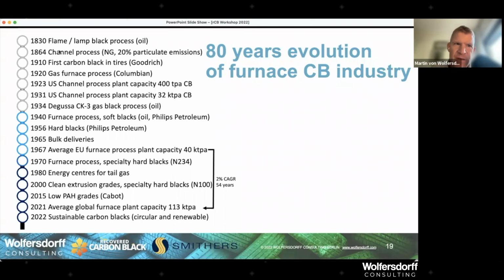But in 1830, we had the lamp black process with the feedstock oil. Then the channel process came up in 1864 based on natural gas feedstock. And the particles were collected in so-called hot houses, in the smoke houses. And about 20% of the particles were not collected. So you could see about hundreds of miles and kilometers away, you could see where there was a carbon black manufacture, because there was a large black cloud over that particular town.